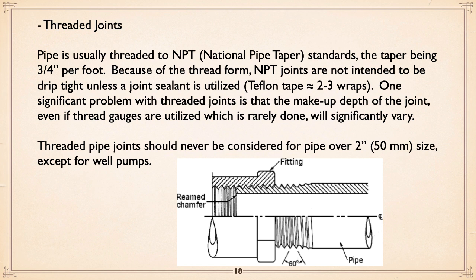A significant problem with any threaded joint is that the makeup depth of the joint, even with thread gauges, is rarely perfect. So the length of a collection of threaded fittings can vary. Threaded pipe joints should never be considered for pipe over 2 inch, except for well pumps. Well pumps have the reason because you're trying to stay within a confining space of the well, so threading is quite common. And to be frankly honest, if they leak a little bit, it just goes back into the well.